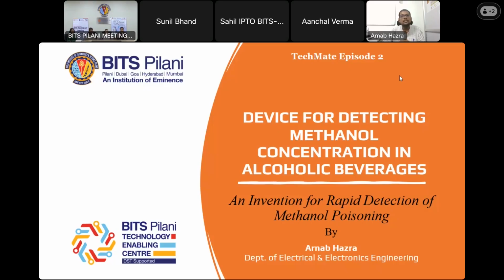So it can successfully detect methanol contamination in different types of beverages. The example I'm showing is methanol added only with ethanol. But if we take other real-time alcoholic beverages, there will be other compounds added, because of some essence, sweetness, and a lot of other things. But in the presence of those, this sensor can detect methanol contamination, which we have tested with multiple samples. Around 4 or 5 samples we have tested, and it's working well.